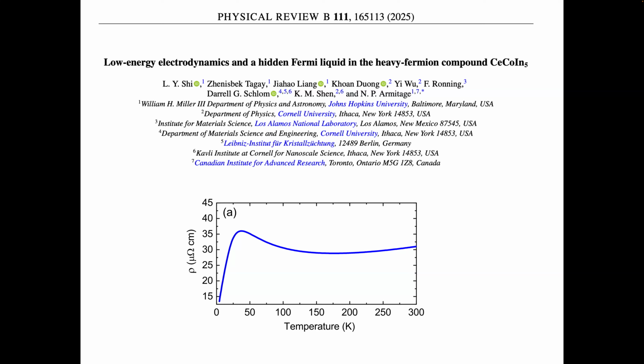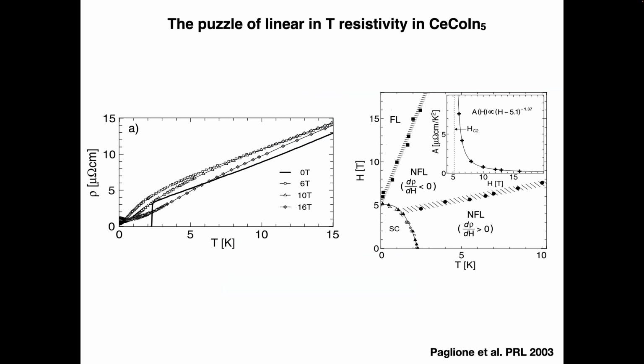And one of the things that's been inferred about cerium cobalt indium 5 is that it also is a strange metal, because it's linear in T in very similar fashion. So maybe I'll just skip that, although this point is also made here: resistivity versus temperature in 0 Tesla. Maybe that's why I will talk about that. Again, you can just see the linear in T here. It was not as obvious on the previous plot, but it's a lot more obvious here. The dark black line is the linear in T resistivity.